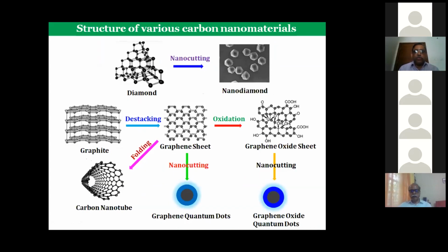Now, how do we really make new materials out of that is the new learning. One can make a nanodiamond from diamond by nano cutting. You can look at the graphene sheet — a graphene sheet can be obtained from graphite, and a small folding can give you the carbon nanotube, cut into small pieces, and that gives you carbon quantum dots. You can also oxidize this to get graphene oxide, make it into small components, cut it, and that gives you graphene oxide quantum dot. This is the whole story about preparing smaller dimension materials from graphene and graphite or carbon derivatives.